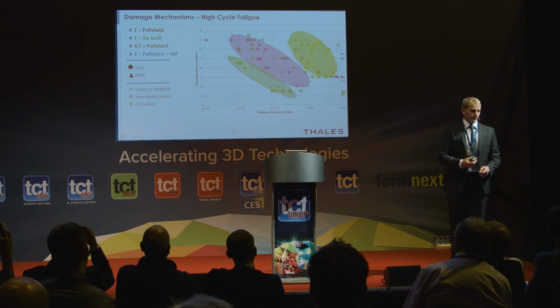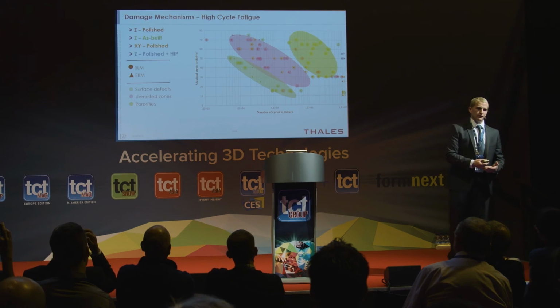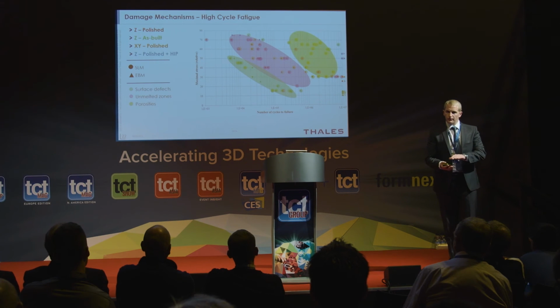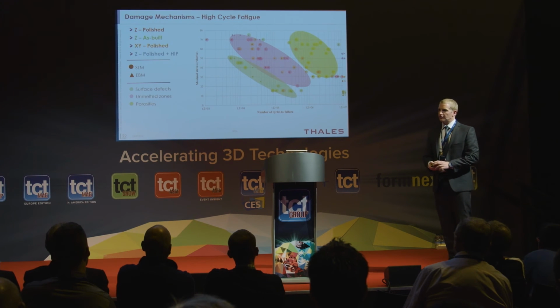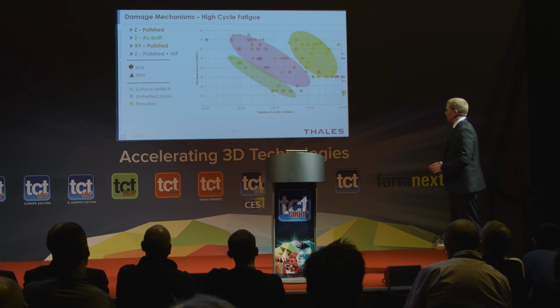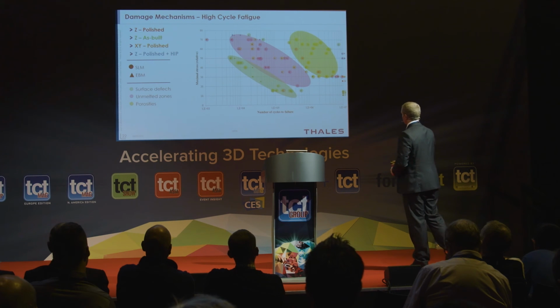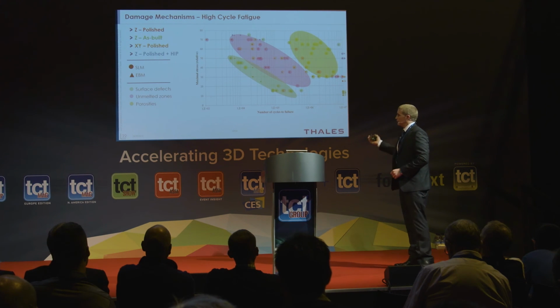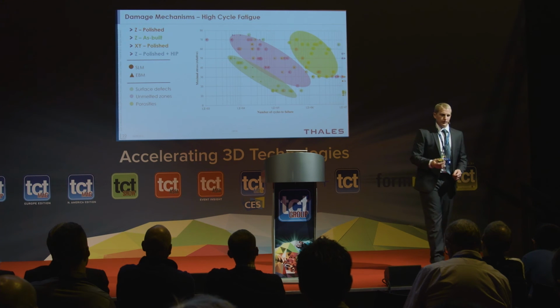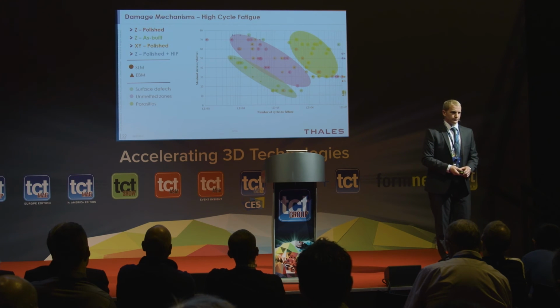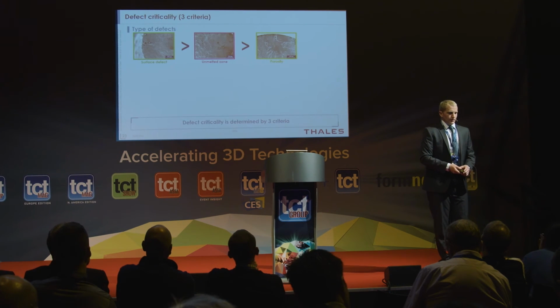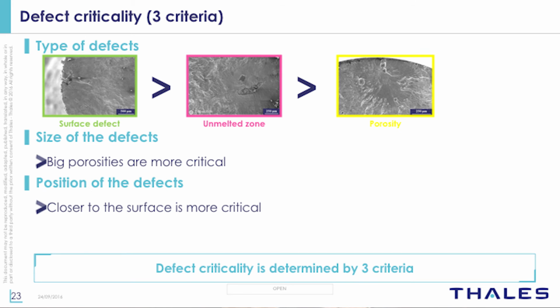The area in the center, this is mainly down to unmelted zones within the part, so more to do with things you can't see from the surface or through penetrant inspection. And then in the top right, we've got failures due to porosities at really high cycles. So again, looking at the defects there, these are the three key areas. So the main one would be surface defects.